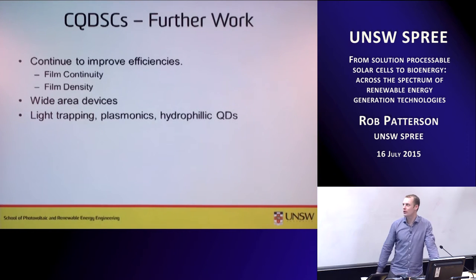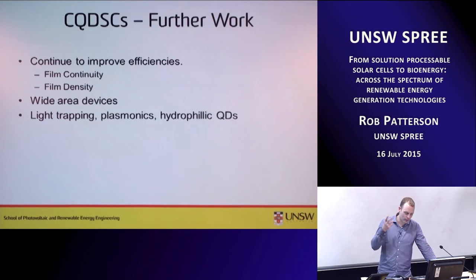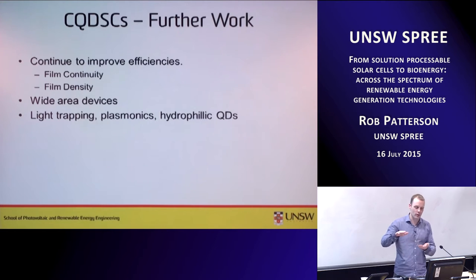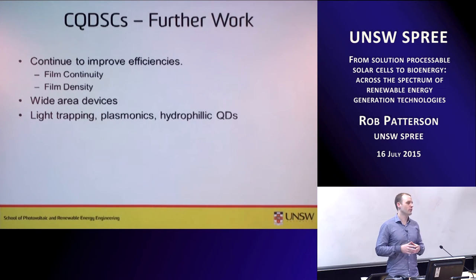And so what are the things that need to be done in order to do that? Basic film fabrication in this material system, I think, is really important. You need to make sure that you have good continuity in your films. From solution processing, you always have to deal with, especially in your hole blocking layer, this ZnO or TiO2, surface tension. When this thing is drying, it has the potential to contract on itself, or to crack during a heating process. There are ways around that. Layer by layer deposition helps a lot. Film density is also an issue, especially for the nanoparticles. You need to get these nanoparticles very close together in order for there to be good transport through your film. We'd like to go to wide areas. I know one of our team members is particularly interested in that.